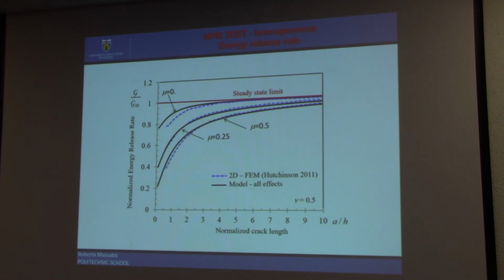So let me show you this diagram, which is my last diagram. This is the energy release rate normalized to the steady-state limiting solution as a function of the crack length. The steady-state limit is in red, and these curves, the black curves, are the solution of our model, and they correspond to 3 different Coulomb friction coefficients: 0, 0.25, and 0.5. And the results are compared with the finite element result in the original paper by Hutchinson and Hutchinson, and you can see how well our model is able to reproduce the behavior for crack lengths which are intermediate.